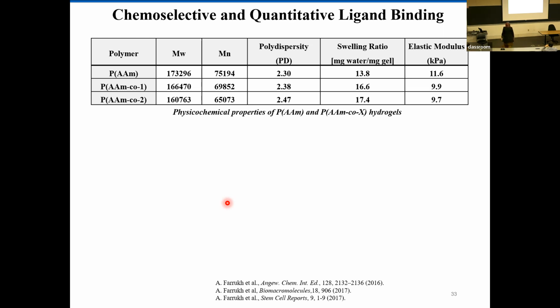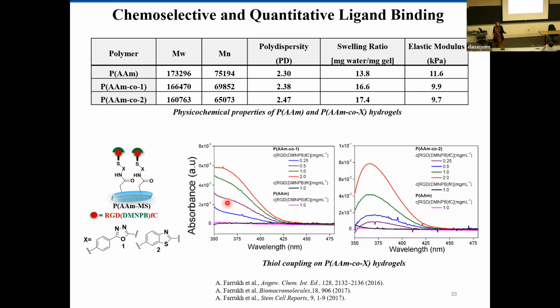Once we had the polymer, the next step was making thin films. First we made the thin films, and then we used a fluorophore just to see if we can really do the coupling. When there is no methyl sulfone, we can see that nothing is binding onto the polyacrylamide. But when we have methyl sulfone-containing comonomers in our polyacrylamide gel, we get quantitative binding of the fluorophore or chromophore on the surface of the gel using this methyl sulfone thiol chemistry.